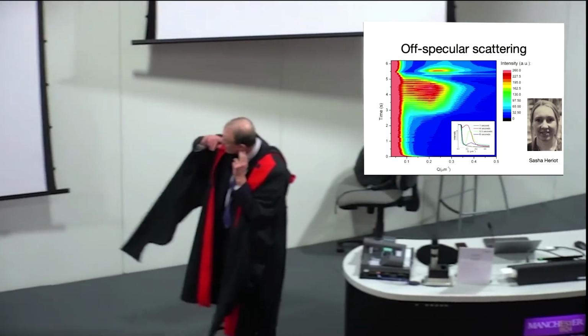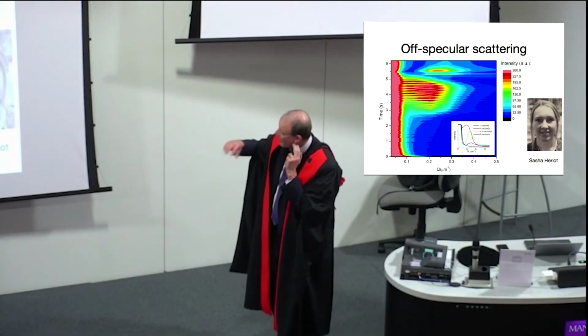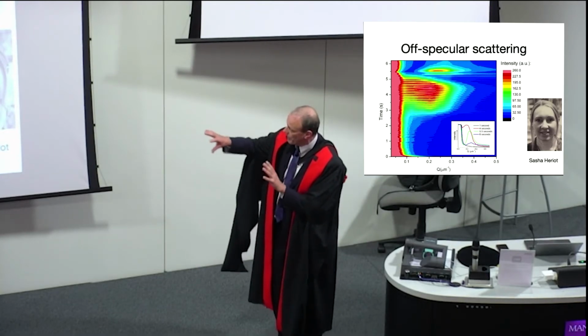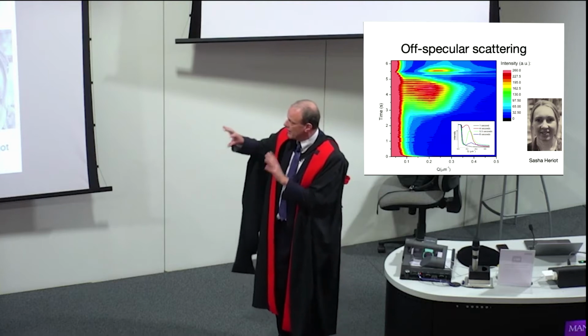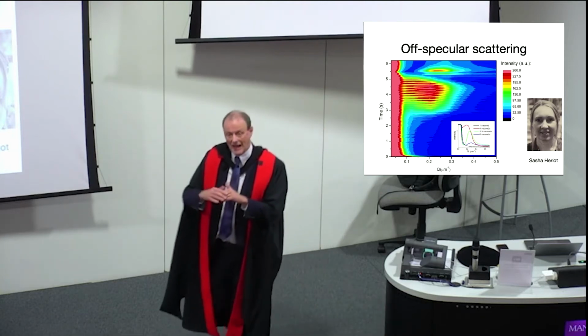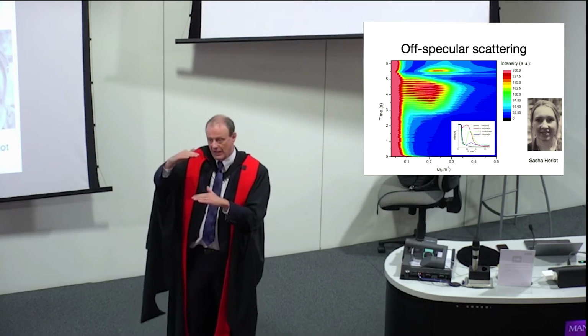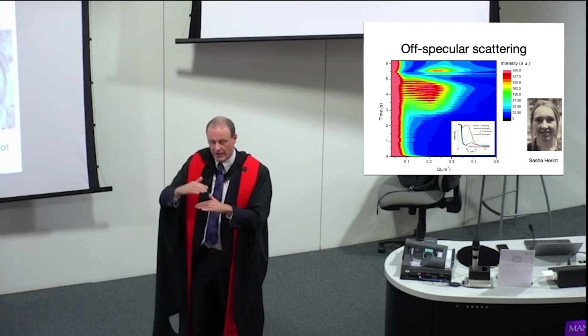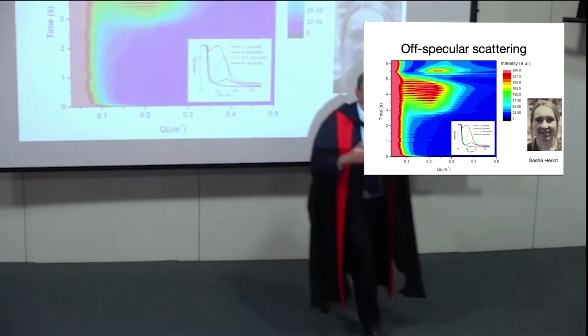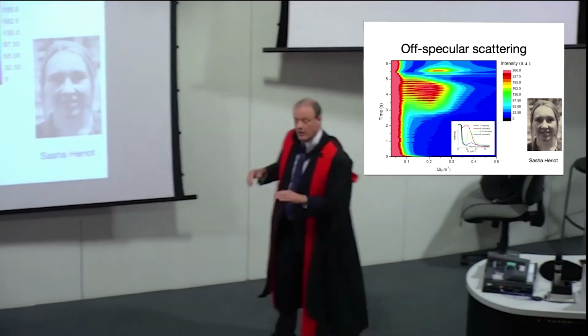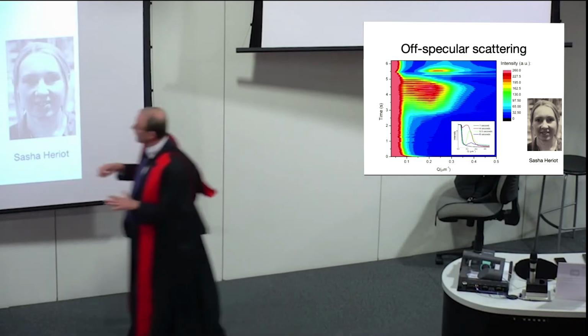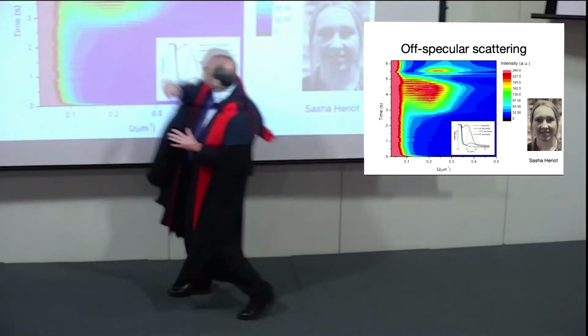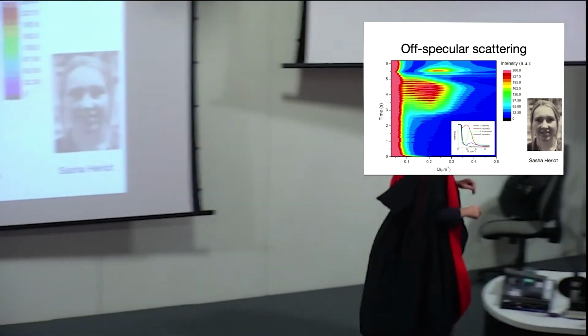Sasha Heriot was the postdoc who produced this very nice data. What's going on is not at all obvious, but the key point is that this kind of data tells you two things. It tells you how the film thins as the solvent leaves, and you can follow the thickness as a function of time essentially by counting these fringes. These fringes come from interference from the light being bounced off the front and back. And you can see what's happening laterally by the appearance of a scattering peak. We were able to interpret that and come up with a model that showed us what was going on.